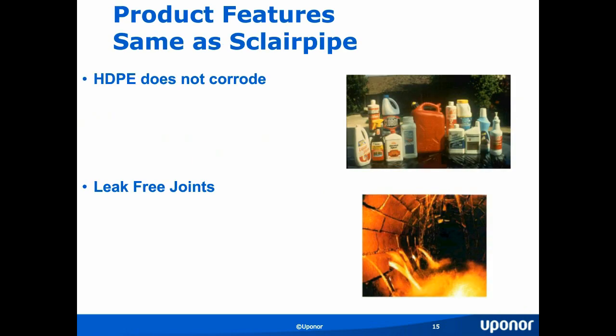Our Weholite pipe is made from exactly the same material as our Sclairpipe material is made from. HDPE does not corrode, and you can see from that picture on the right-hand side that all those household cleaners, corrosive, acidic, whatever the case may be, are in polyethylene containers. And for that reason, high-density polyethylene Weholite stands up to corrosive conditions so well.